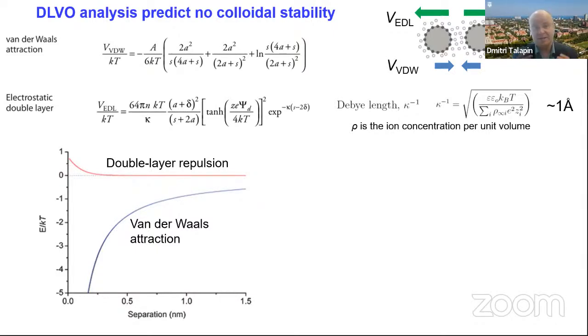The idea is that if you want to make a colloidal dispersion, you need net repulsive pair potentials. When two particles come close together, they should feel repulsive potentials and should not aggregate. There will always be an attractive component, van der Waals attraction, and you need a repulsive term that is stronger than it. In molten salt, since it's a very polarizable medium, the Debye screening length, if we define it classically, will be on the order of 1 angstrom. It's an extremely concentrated electrolyte, and that's why electrostatic repulsion will always be inferior to van der Waals attraction. So these colloids should not exist. They should aggregate and fall to the bottom.